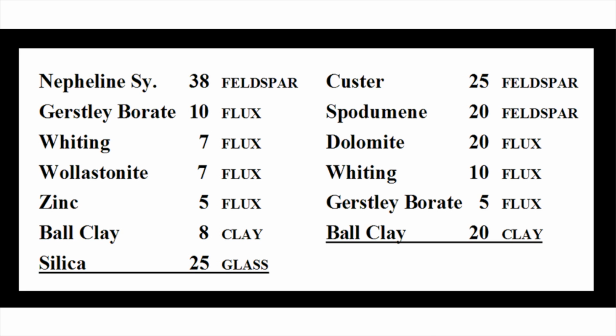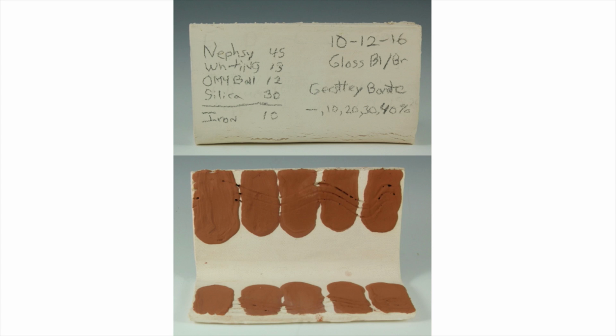Now back to adjusting a glaze. I started using this glaze testing method of adding increments of an influencing ingredient to a base glaze on an L-shaped tile way back as a graduate student at Alfred, where I was asked to teach the raw materials lab class to the undergraduates. As done many times, we began by testing combinations of feldspar with increasing amounts of flux, mixed up dry, packed into a tiny thimble, and then transferred onto a flat tile, retaining the thimble shape.